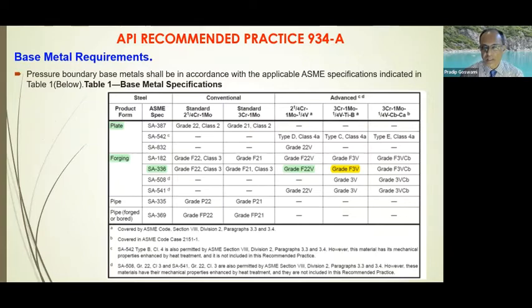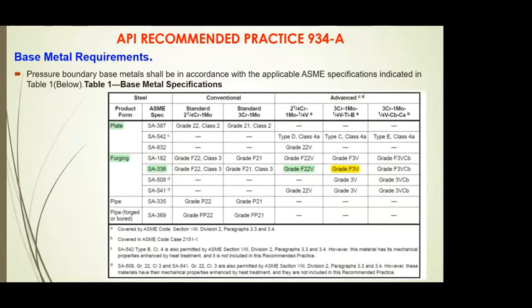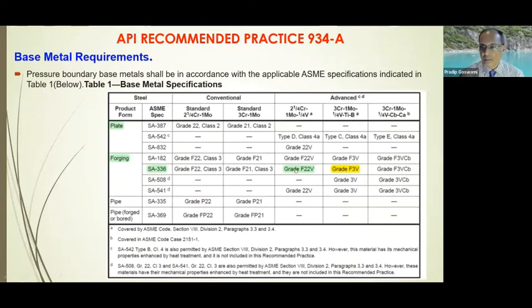Following grades of material are generally covered by this particular specification. As you can see here, 2 chrome 1 moly quarter vanadium, that is grade F22V. V stands for vanadium modified, and F22 is 2 chrome 1 moly grade. That is the most popular, although I would think that in the industry, in some refining circuits, grade F3V, that is the 3 chrome 1 moly quarter vanadium, that steel is also used. But by and large, F22V is the most common material which the fabricators are familiar with, and this is used heavily for fabrication of hydroprocessing reactors involving this intended application.